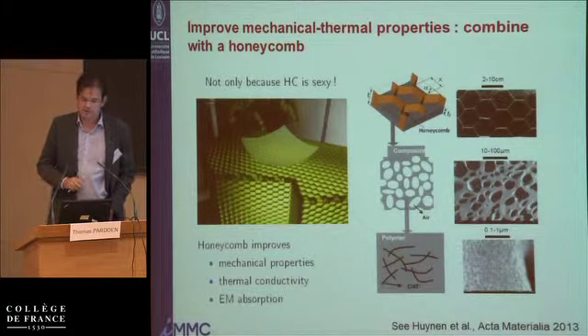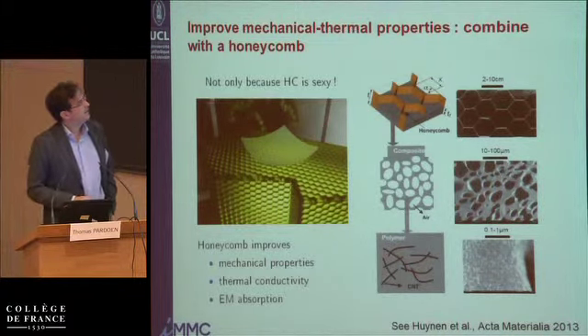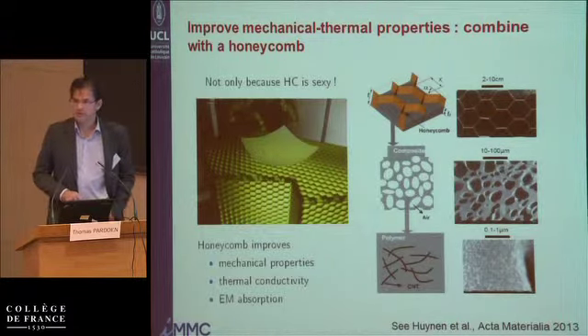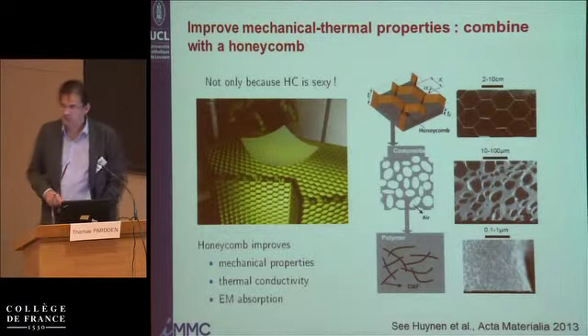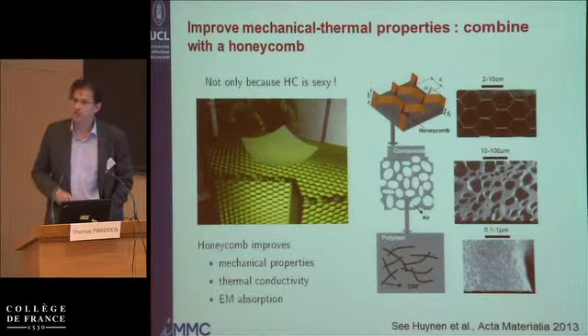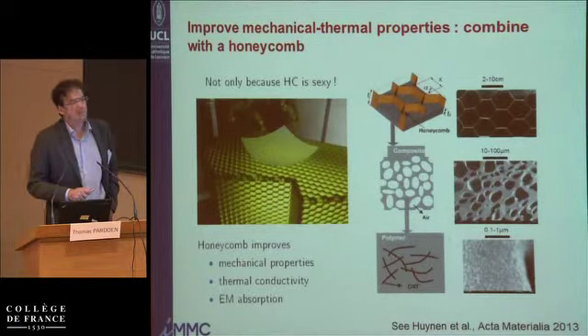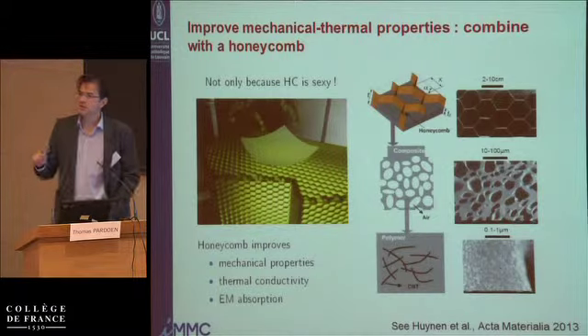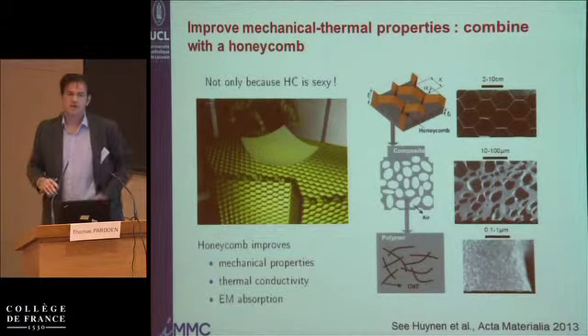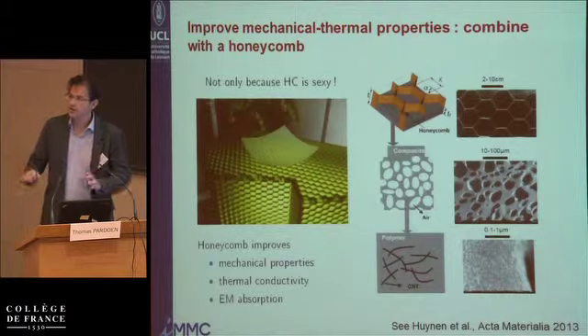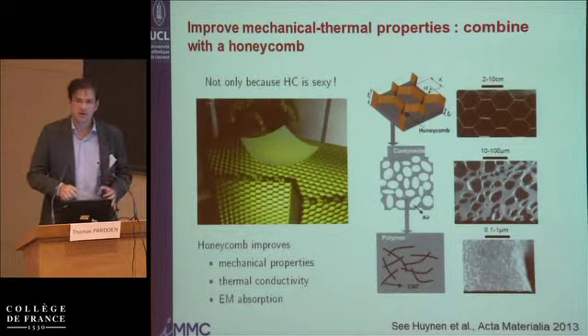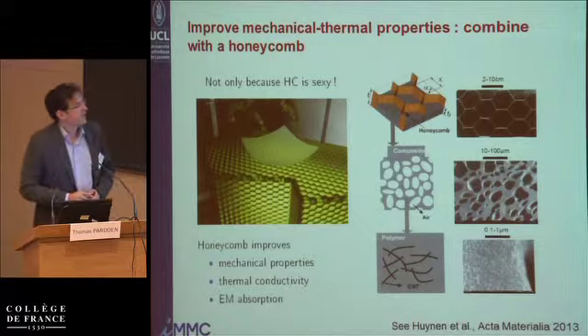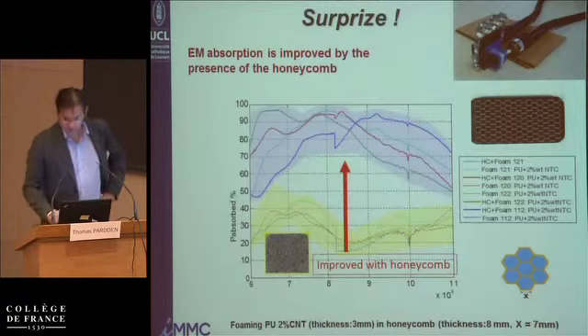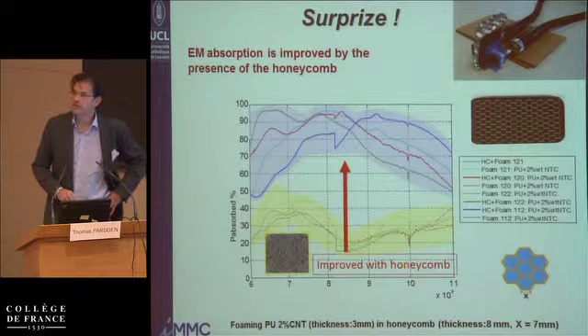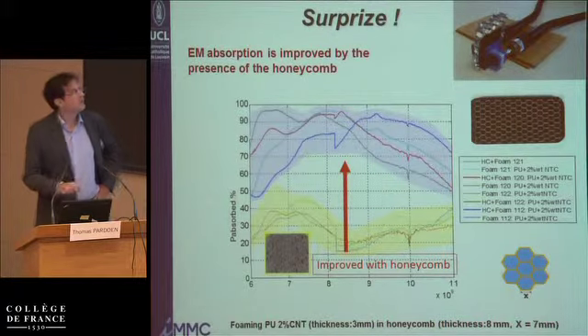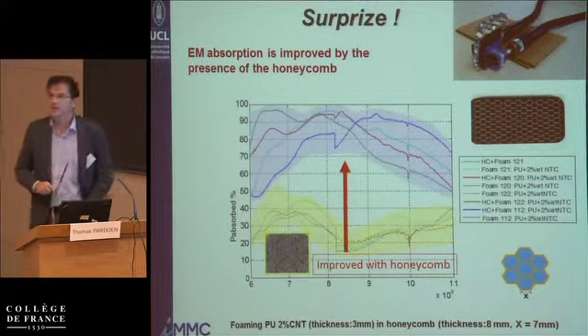Okay, but like I said, we could get relatively good absorption, but the question was, can we do better? And the idea was to mix this foam with aluminum honeycomb. Initially, the idea was only for mechanical purpose. I thought that by putting this foam inside the honeycomb, we could improve the mechanical properties while not changing the electromagnetic properties. And the good news is that by introducing the foam inside the aluminum honeycomb, we also got an improved electromagnetic absorption.